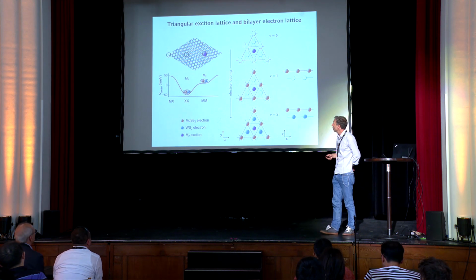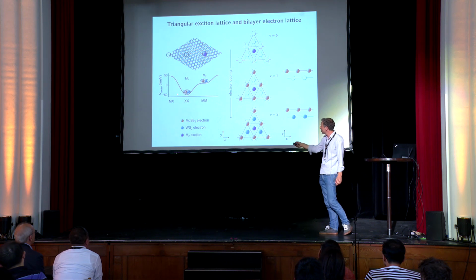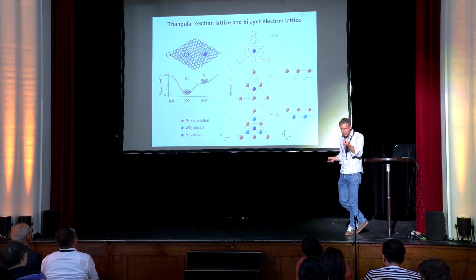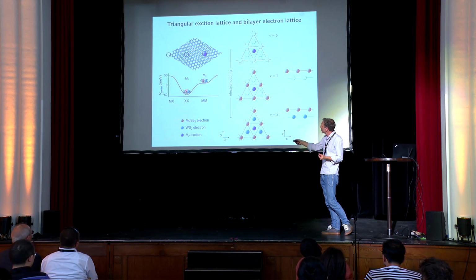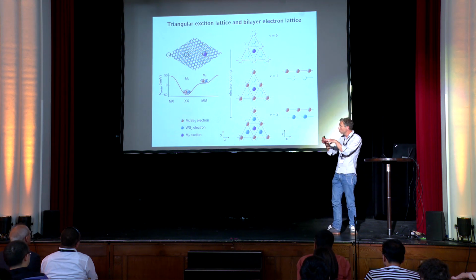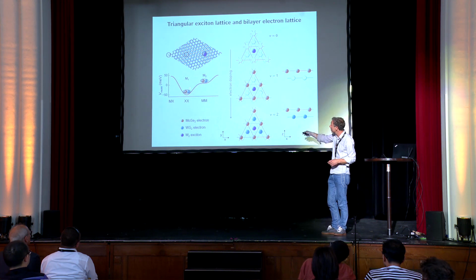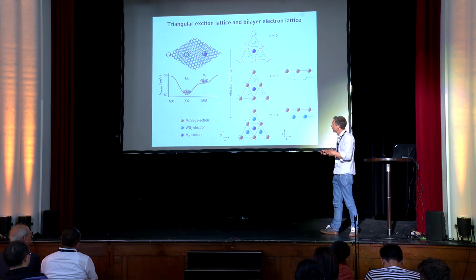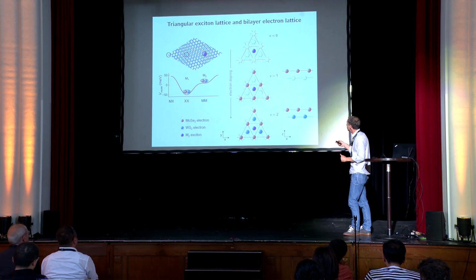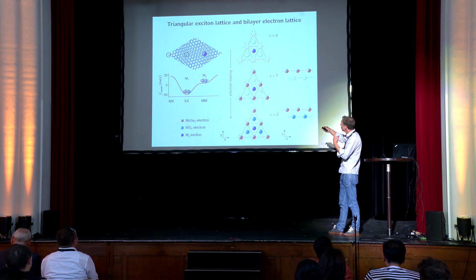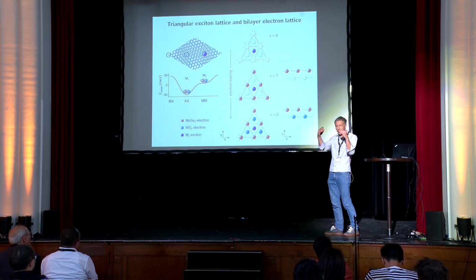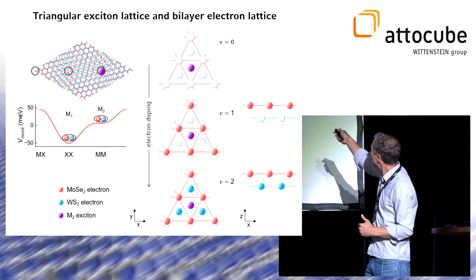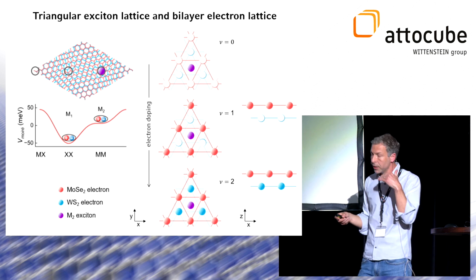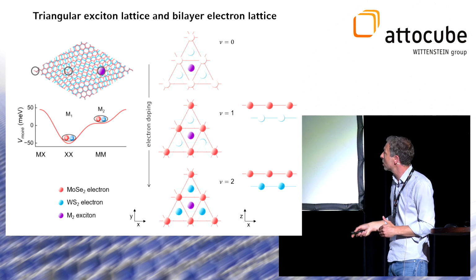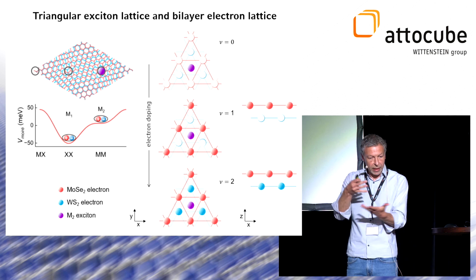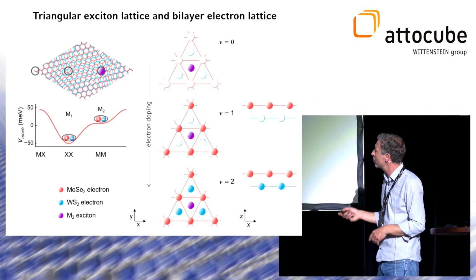So in such a system, you can imagine now that as we add electrons, they will seek the potential minimum of moiré co-localizing with the moiré exciton 1. There is a moiré exciton that can act as a remote sensor of the charged lattice, having only a minor wave function overlap with the electron that we add. It turns out that according to the charging of the system that we have learned to interpret, this exciton M2, that we use as a sensor, will see a sequential loading of the primary triangular lattice in the monolayer, molybdenum diselenide, until its Mott insulating state, and only then sequentially will the secondary layer, the tungsten layer, charge, such that the system actually realizes a staggered bilayer model with vertically offset 2 sublattices, 1 in molybdenum, 1 in tungsten.